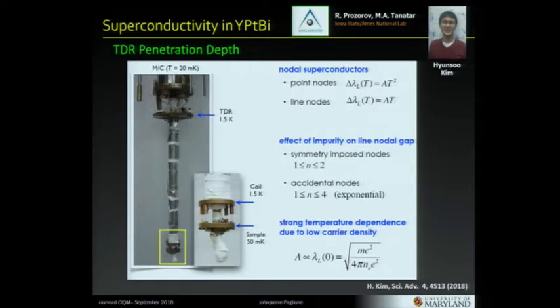The key to this experiment is that the penetration depth, measured using a technique called tunnel diode oscillator, is inversely proportional, square root proportional, to the density of states. The carrier density. So if you remember, this system has an extremely small carrier density. That makes it extremely hard to measure specific heat, thermal conductivity, etc. All the thermodynamic properties that scale with density of states are hard to measure, or they show nothing, basically, in terms of going through the superconducting transition. This is actually inversely proportional to it, so it's a very large signal.